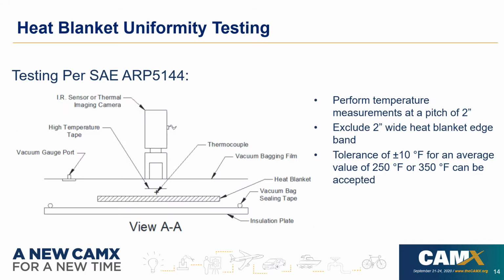The next step after we manufacture a blanket, we would inspect it for uniformity. We do 100% inspection using a test method for SAE ARP 5144. In our case, we use an infrared thermal imaging camera. Once we've taken a picture at typically 350 degrees, we would analyze the image. To pass under the specification, there's a 2-inch pitch, and we would exclude the 2-inch edge band around the blanket. And then to pass this requirement, we would need to be within plus or minus 10 degrees at 250, or most notably for our internal testing, 350F.